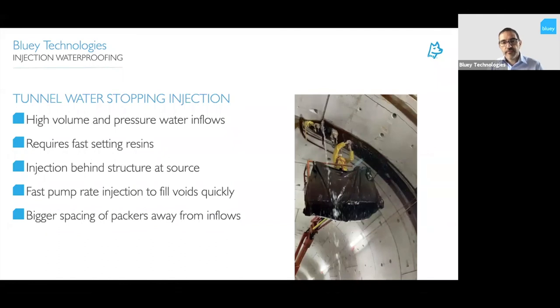You can see there, we're under about 40 metres of water there, below Sydney Harbour in that one actually. And you can see the water just off to the side of the applicator there that's coming through that joint. And that's what we're actually trying to seal. So through that packer that is just installed, we'll be injecting a very fast setting resin. So that'll foam and start reacting within about 10 seconds and it will form a structure within 1 to 2 minutes. And as we're injecting that, you'll be able to see that leak seal almost instantaneously. We were out of there within less than an hour. It's drilling one hole, injecting the resin, sealing that up completely, and then being able to walk away.